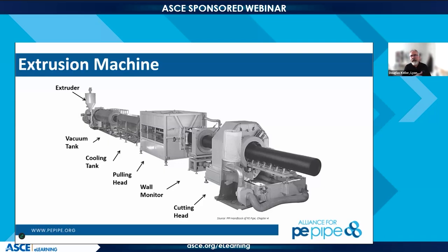It then goes into secondary cooling tanks. So we're trying to take that heat back out to solidify the material. It is being pulled by the pulling head or the pulling machine once it comes out of the die. We go through wall monitoring to make sure that we're making the diameter and the thickness that we need. And then the pipe is cut in whatever lengths that you need. So we can supply pipe in stick form, which is typically 6-inch diameter and above, or we can also provide it in coil form, which is 6-inch and below, depending on what your application is and what your end use for the material is.